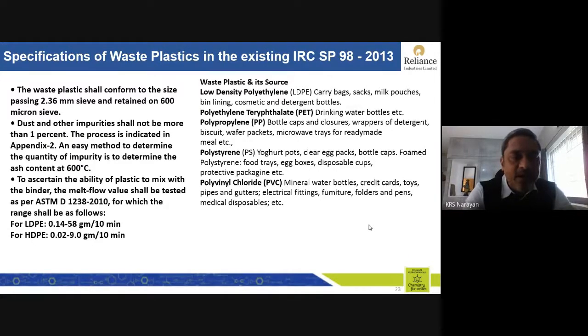Specifications as per the IRC 98 code is the plastic material should conform to the size of 2.36 mm. Should be passing this 2.36 mm and retained by the 600 micron sieve. So you will have a material which is only 2.36 mm to 600 micron. That's 0.6 millimeter in size. It would be almost like a grain of sand, probably. So dust and other impurities shall not be more than 1%. So it's very, very difficult to find any wet carry bag or contaminated carry bag with less than 1% of impurity. So an easy method to determine the impurity was to determine the ash content at 600 degrees Celsius.